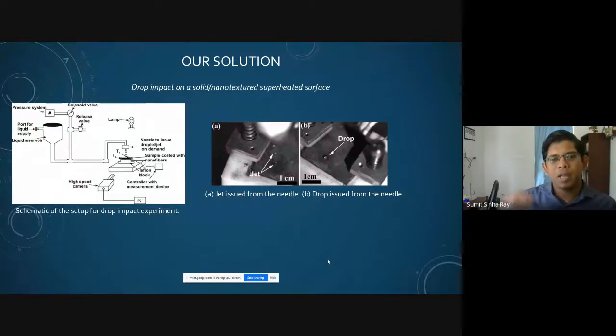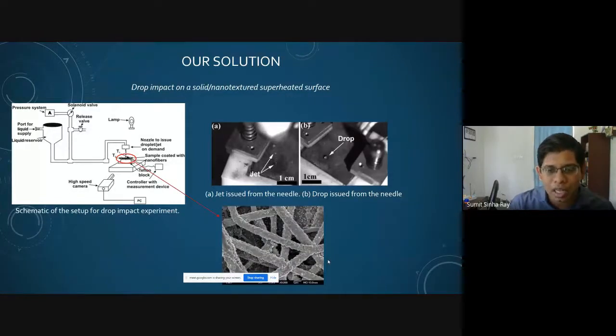So what if we issue a single droplet onto the surface and allow it to boil on the surface, but the most important question was how to make it stick onto the substrate, and then just cool that area. And once one droplet evaporates, the next droplet will come, or we can have a jet onto the surface, and in that sense, the net heat removal in terms of watt per centimeter square would be much higher. So in this regard, my job was to develop these kinds of surfaces.